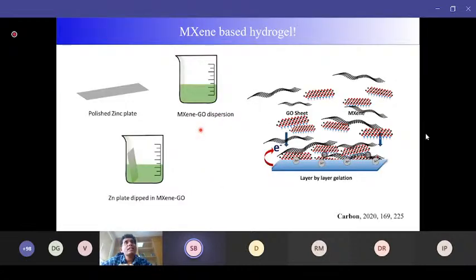And we inspected whether we can assemble those MXenes exactly the same way as the graphene, which we did. We tried that initially. Then we found that whenever this MXene gets assembled over the zinc foil to give a hydrogel, that hydrogel is very brittle, and actually it is not forming any freestanding structure. So to make a freestanding structure, we inspected why we are not getting it. We thought that these MXene sheets are ceramic in nature as compared to graphene, which is polymeric in nature.